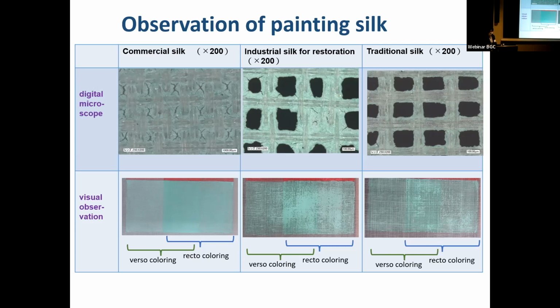I compared samples of modern infilled silk, that is to say, pieces of modern silk used to fill in traditional silk painting during conservation, with samples of traditional silk. Both showed gaps that allowed verso pigment to be seen from the recto, which indicates that traditional painting silks had an effective textile structure for the showcasing of verso coloration techniques. Furthermore, I observed that pigment is applied on silk fiber more evenly in traditional silk, like this one. This suggests that fiber shape influences pigment fixability because traditional fiber has a flat surface.